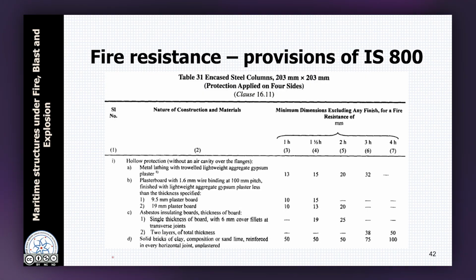However, as we discussed, this kind of an approach also suffers from similar limitations as earlier, that in this case there is no dependence on the level of load. So, if under the cold conditions the capacity is very close to the demand, then under fire conditions such members will fail faster. Whereas, if there is a large amount of capacity available compared to demand, then such members may fail much later in fire. So, this is where calculations of temperature and strength that we have been doing are very important.